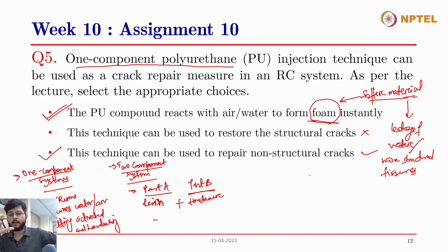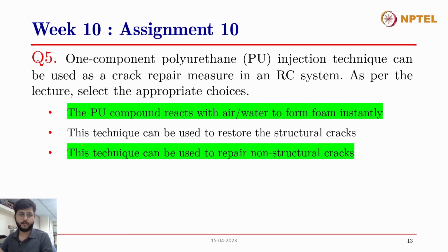If only PU is injected, then that is only to stop a small crack, the leakage of water across the small cracks. So if only PU is getting used, then that is to repair only the non-structural cracks. If you want to carry out a structural crack repair, if there is no leakage of water, then you can directly go ahead with epoxy. But if there is a leakage of water over there, then you have to first stop the leakage of water using PU, then you can carry out an epoxy repair. So in this case, these two are the correct answers, right?